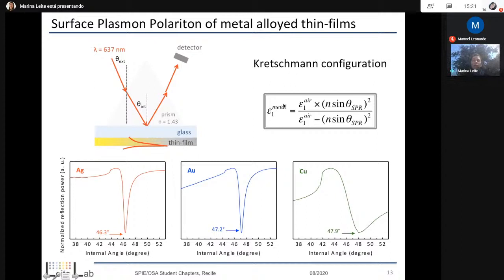So you can see here how we can determine epsilon 1, okay, not the whole permittivity, but the real part of the permittivity, epsilon 1, as a function of the permittivity of air, which we know very well, the angle here of our surface plasmon propagation, and the refractive index here of our material. So that becomes very straightforward in reality.